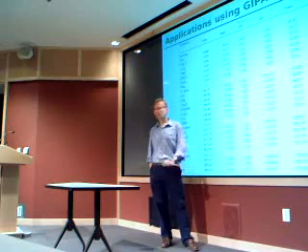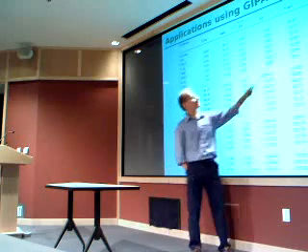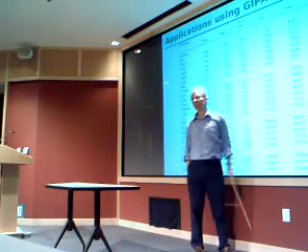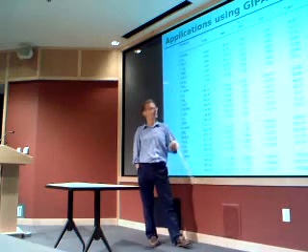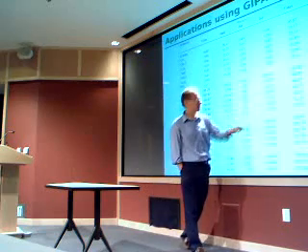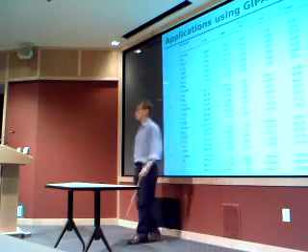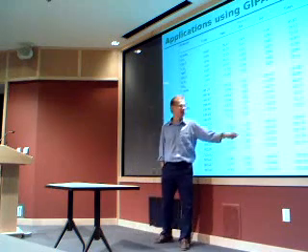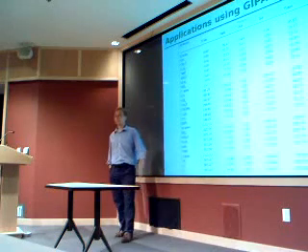But this was also interesting in the beginning to see if you take the all-electron values and values from GIPAW, you get usually very close. So they are within 1 ppm, so these are ppm, parts per million. And somewhere you get some divergence of a couple of ppm, but really the range can be 100, 200. So if you have a difference of 4, it's still very small. So the accuracy of GIPAW seems to be good.